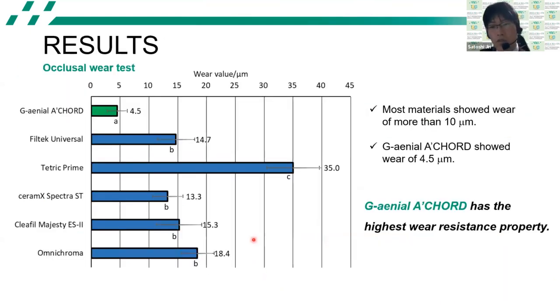This is the result of the occlusal wear test. Most products show wear of more than 10 micrometers. On the other hand, G-aenial A'CHORD shows wear of 4.5 micrometers, which was the smallest among these materials. This result indicates that G-aenial A'CHORD has the highest wear resistance among these materials.